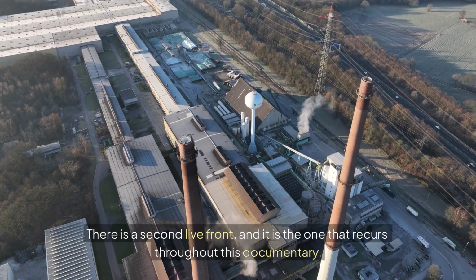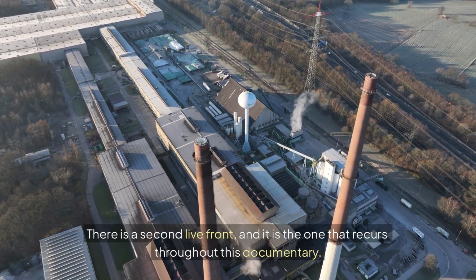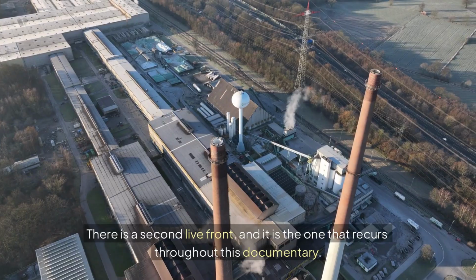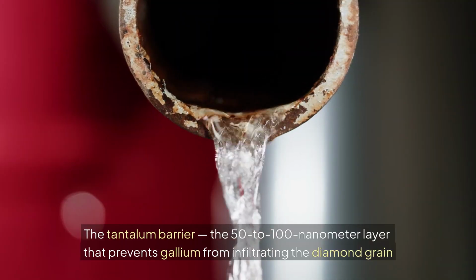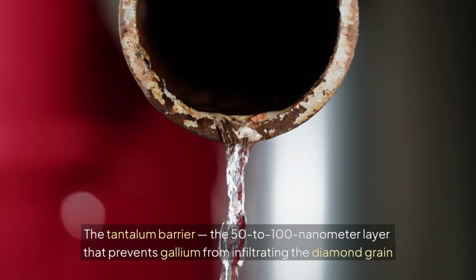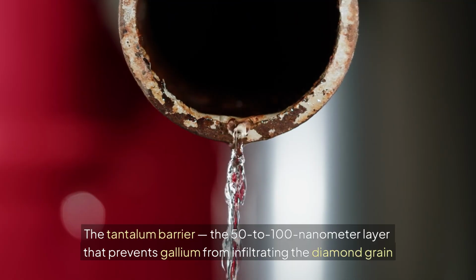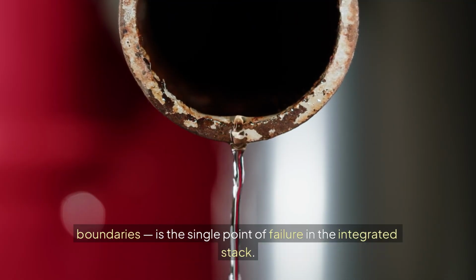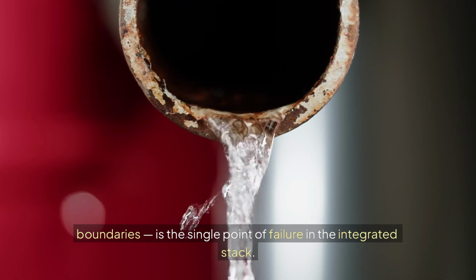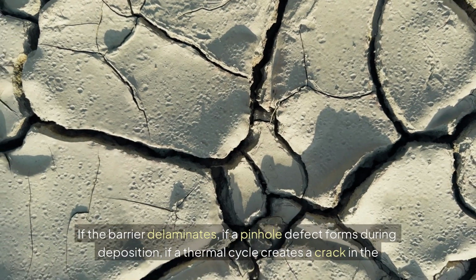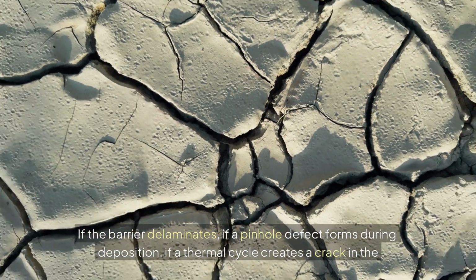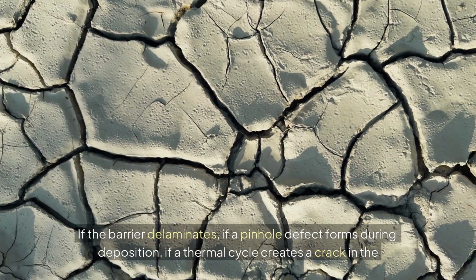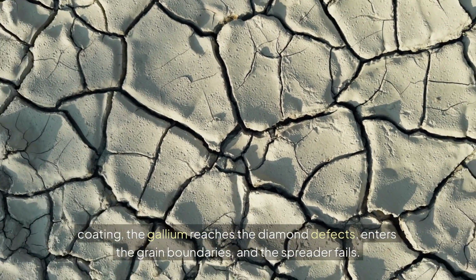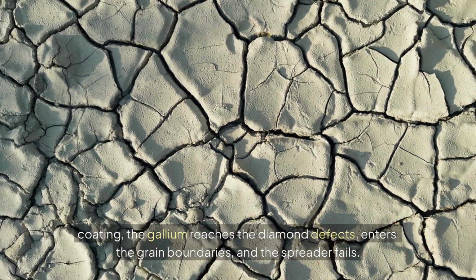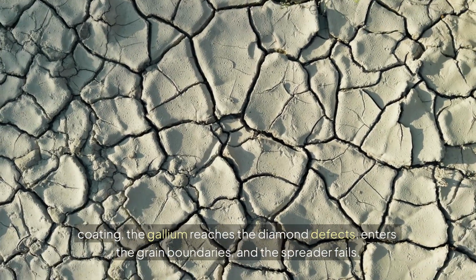There is a second live front, and it is the one that recurs throughout this documentary. The tantalum barrier, the 50 to 100 nanometer layer that prevents gallium from infiltrating the diamond grain boundaries, is the single point of failure in the integrated stack. If the barrier delaminates, if a pinhole defect forms during deposition, if a thermal cycle creates a crack in the coating, the gallium reaches the diamond defects, enters the grain boundaries, and the spreader fails.